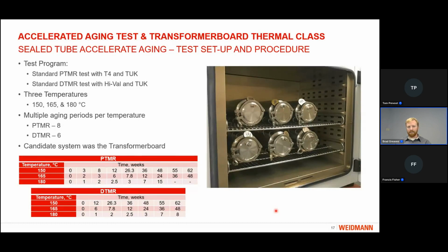Specifically for the testing that we had done, we had a test program with our standard material ratios, both the power transformer ratio with T4 and TUK, and our distribution transformer ratio with high val and TUK. We used the same 3 temperatures as the IPS, the 150, 165, and 180 degrees C, and we had multiple aging periods per temperature. We had slightly different numbers for the ratios. For the power ratio, we actually had 8 in most cases, and for the distribution, we had 6. And you can see in the tables below the actual time periods that were aged for these systems.